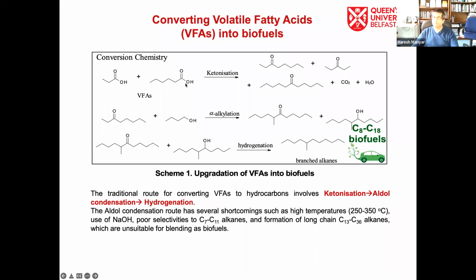So in the reaction pathway, two molecules of the acid react. The reaction is called ketonisation. It produces a ketone along with a molecule of water and CO2. And these ketones can be a mixture of different ketones because we have a mixture of different fatty acids. These mixed ketones, symmetric or asymmetric depending on whether it is a cross ketonisation or a ketonisation between the same molecule, can then be alpha alkylated directly by reacting with renewable alcohols. The alcohols we are talking about are of biomass origin, renewable alcohols like ethanol, propanol or 1-butanol, which can be obtained sustainably. So we get alpha alkylated, elongated chain ketones, which can directly be hydrogenated to branched alkanes.